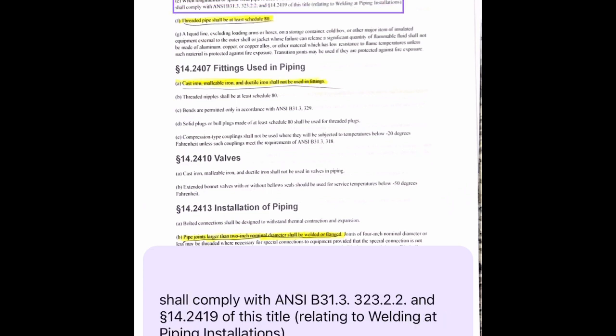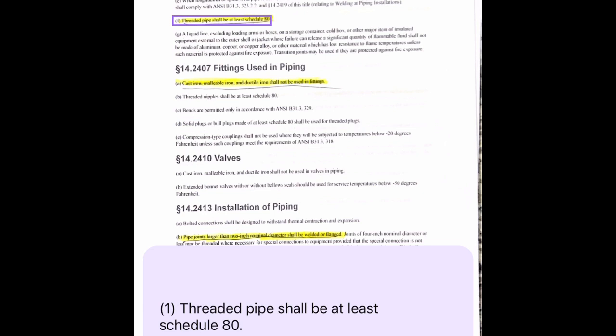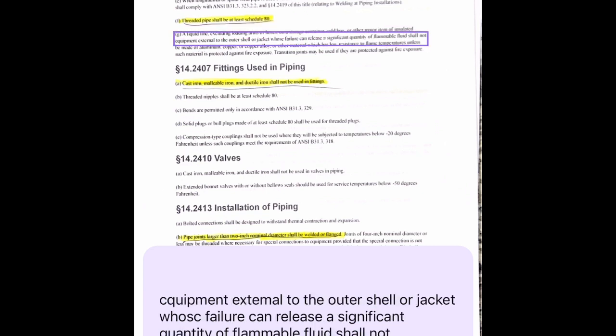When longitudinal or spiral weld pipe is used, welded with or without filler metal, the weld and heat affected zone shall comply with ANSI B31.3, 323.2.2 and Section 14.2419 of this title, relating to welding at piping installations. F. Threaded pipe shall be at least Schedule 80. G. A liquid line, including loading arms or hoses on a storage container, cold box or other major item of insulated equipment external to the outer shell or jacket, whose failure can release a significant quantity of flammable fluid, shall not be made of aluminum.